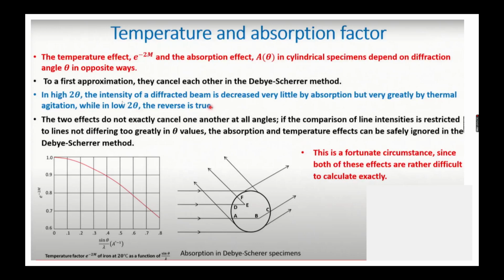So at high 2 theta, the intensity of a diffracted beam is decreased very little by absorption, but very greatly by thermal agitation, while at low 2 theta value it is vice versa. So when Bragg's angle 2 theta is higher, the intensity of the diffracted beam decreases by a very small amount due to absorption, but due to thermal agitation it decreases very greatly. So this is what it is saying.